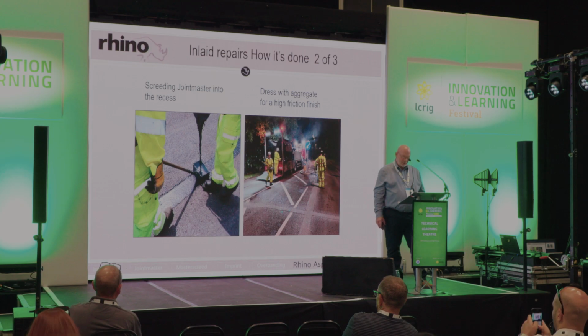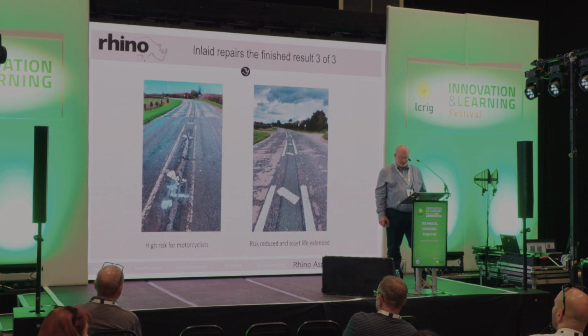We then clean with hot compressed air and apply the material to the recess. In this case, it's a joint master repair. That's finished flush with the surrounding road surface. We then dress it with a high PSV aggregate and sweep the remaining excess aggregate from the surface.